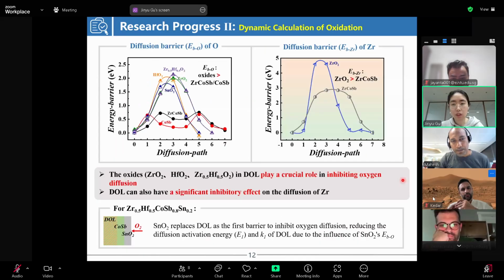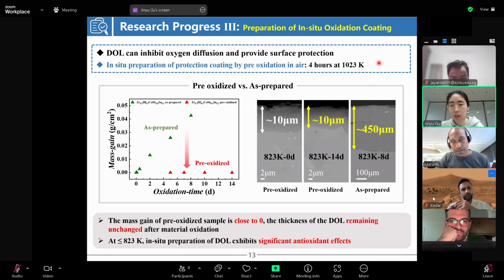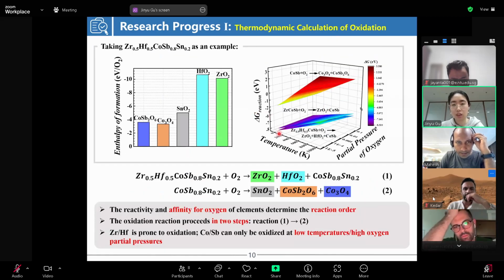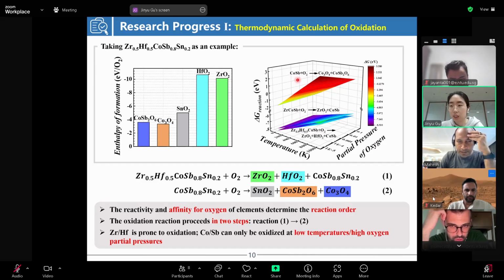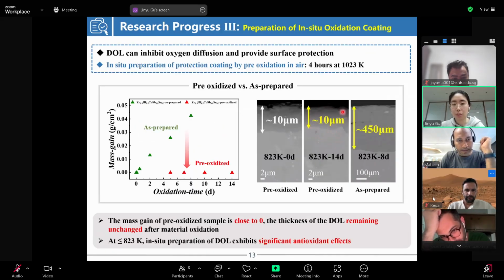Actually, except for the pre-oxidation at high temperatures, if we put the sample in a low oxygen partial pressure, maybe at only 800 Kelvin, it will also generate the DOL, because of the Gibbs free energy: if the temperature is high or the partial pressure of oxygen is low, the oxidation of the zirconium cobalt antimony will not occur. So we can choose another method to prepare the DOL, but I choose this method because it takes shorter time. Okay. Yeah, fine. Thanks.